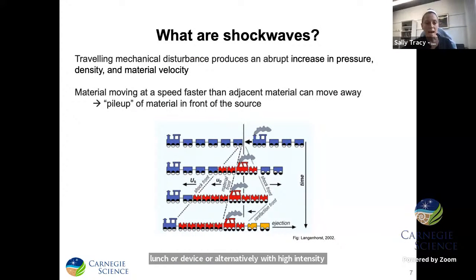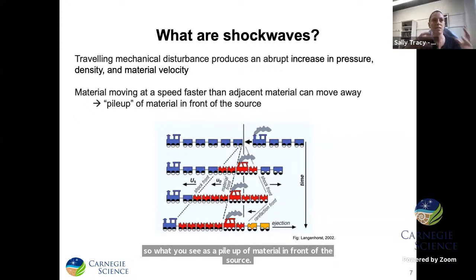So before I jump into the technical aspects of these experiments, for those of you who may be unfamiliar with the idea, a shock wave is really just a traveling mechanical disturbance that gives rise to a step-like increase in pressure, density, and material velocity as it moves through a material. So effectively what's happening is that the material is moving at a speed that's so fast that the adjacent material in front cannot get out of the way fast enough. And so what you see is a pileup of material in front of the source. So that's our high density, high pressure state.